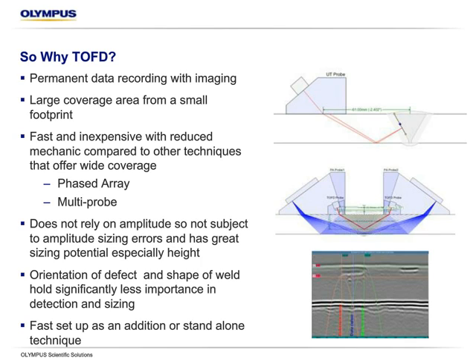It does not rely on amplitude. With most ultrasonic techniques, one of the downfalls is we base everything off a reference reflector, which are perfect things: notches, side drilled holes. The reality is flaws are very multifaceted, they're misshapen. So amplitude techniques work great, but there's some inherent error that goes with things like negative 3 dB, 6 dB sizing. So you never really have a beam half on and half off a flaw.